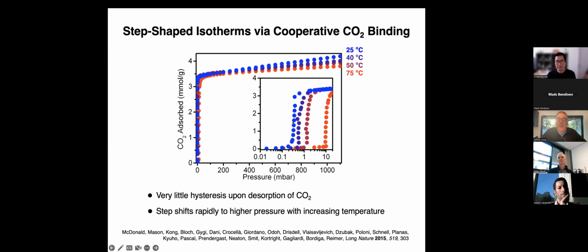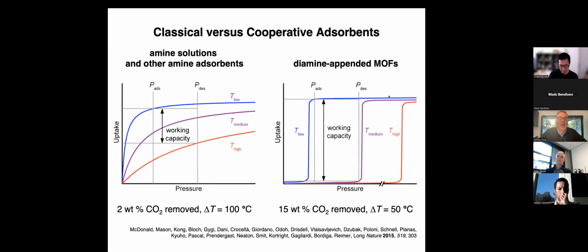And you can also see here, these are adsorption isotherms collected between 25 and 75 degrees C. As we increase the temperature, those adsorption steps move rapidly to higher and higher pressure. Also, the capacities here are generally 3 to 4 millimoles per gram, meaning up above 15 weight% CO2 uptake. So these are high capacity, and you can swing the full capacity of the material because of the step-shaped adsorption isotherms. And so this is the main advantage of these cooperative adsorbents compared to amine solutions or other amine adsorbents. You can do a small temperature change, say 50 degrees C, and have a large amount of CO2 removed in each swing. So lower temperature, of course, means lower energy consumption and lower cost.